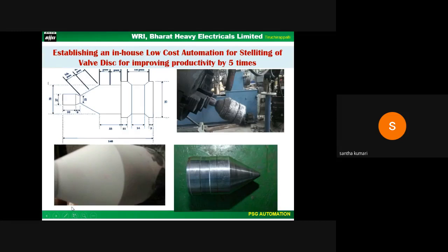But with automation using the positioner, you can see here the positioner and the XY cross slide with controller and the continuous feed wire by the FCAW process, we were able to complete it in 2 hours, including the interpass time. And another major advantage achieved by this is the way of overlaying. We were able to avoid the intermediate heat treatment cycle in case of P91 material.